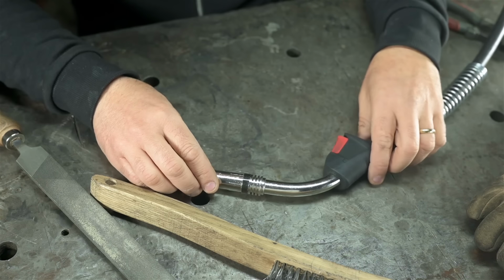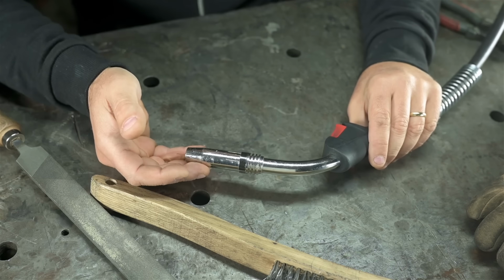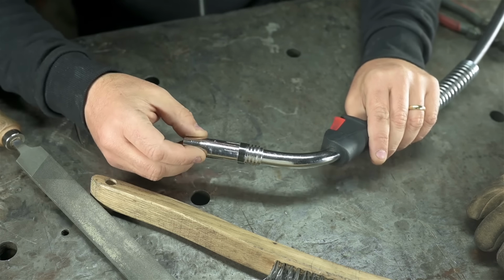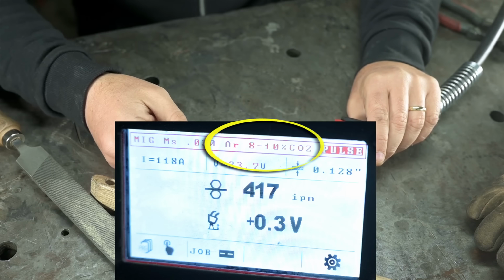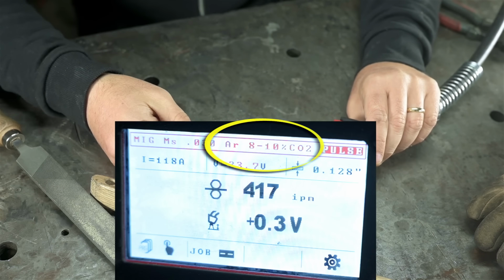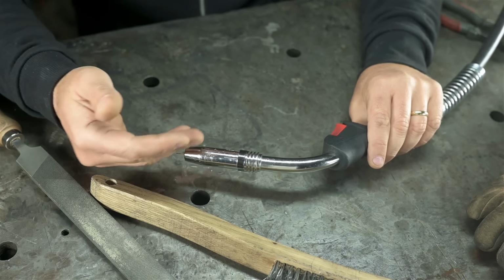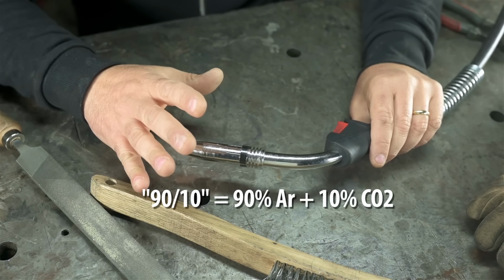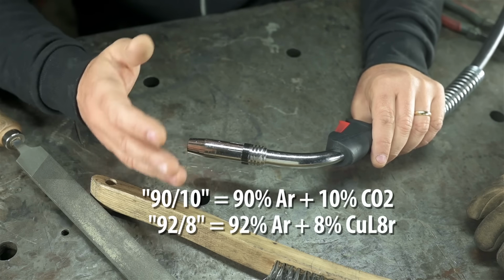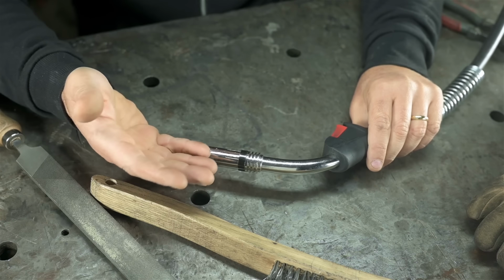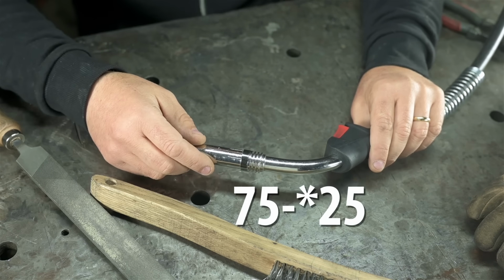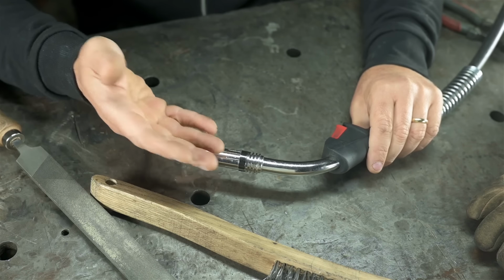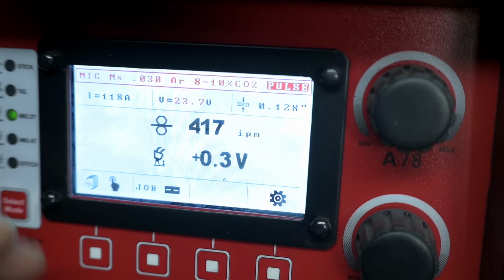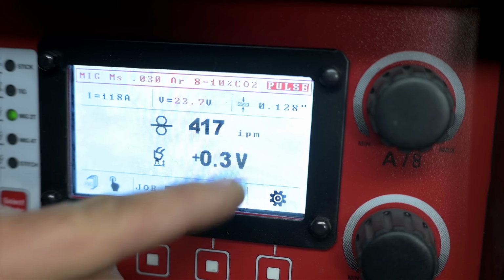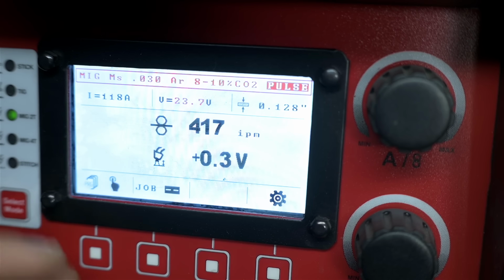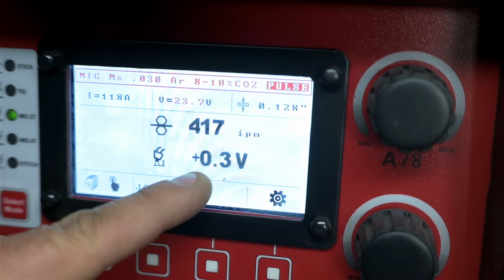I don't know if they're all the same or not, but this HTP wants mostly argon with 8 to 10% CO2 mixed in. If you look close, it says it right on the screen. Pick the program you want, see which mix it recommends, or is required. I'm currently using a 90-10 mix. I have no grounds for this, but I have a feeling that 92-8 might be better. But I can tell you it won't work very well with your standard short circuit 75-25 or even 80-20. If it did, I'm sure they'd list it on the machine. If you're curious, I ended up with the 128 setting, even though my tubing physically measures closer to 120. The voltage adjustment definitely makes a difference.